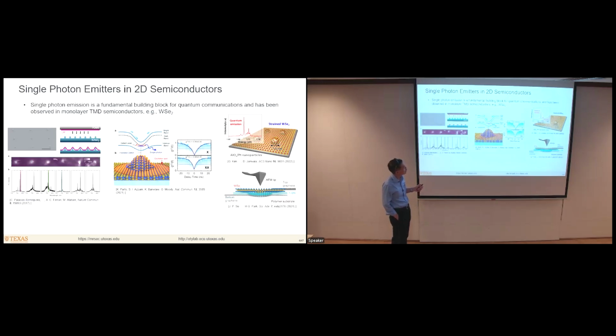And what happens to enable single photon emission is believed to be what's shown here. When you have tensile strain, then the band edge energies shift in a way that reduces the energy band gap, okay, so that excitons in these materials, bound electron hole pairs, move towards the region with the greatest tensile strain. And then at the same time, because these band edge energies are coming down, then there is a hybridization between the dark exciton band. That's the exciton band where optical recombination corresponds to a spin-forbidden transition. There's a hybridization between the dark exciton band and a defect level in the material, such that when the exciton recombines, a single photon can be emitted from the defect level. Right, so that's the basic idea.